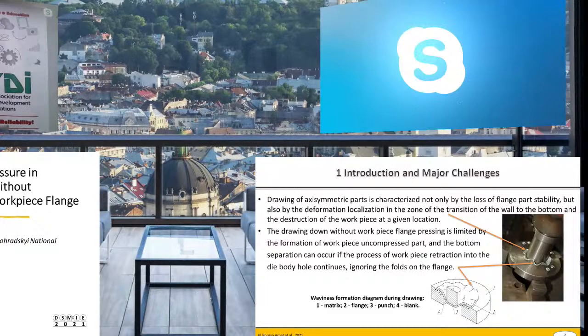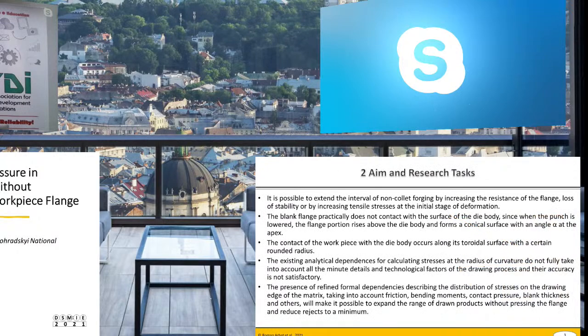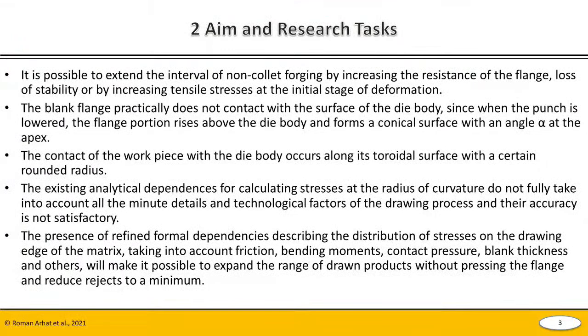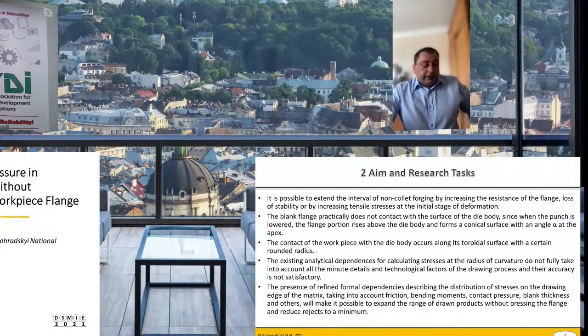Next slide, number 3. It is possible to extend the interval of non-collet drawing by increasing the resistance of the flange to loss of stability, or by increasing tensile stresses at the initial stage of deformation. The blank flange practically does not contact with the surface of the die body, since when the punch is lowered, the flange portion rises above the die body and forms a conical surface with an angle alpha at the apex. Therefore, the contact of the workpiece with the die body occurs along its toroidal surface with a certain rounded radius.